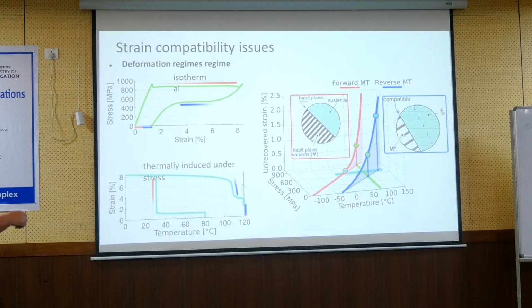So what? Maintaining the temperature below austenite start, right? What is the temperature? Okay, this is just the figure which shows the superelasticity at probably quite high temperature, so the stress is very high. We normally don't use 900 megapascal, it's too much. What are the temperatures in those tests? It's not stated. I estimate, if this is a superelastic wire, something like 100 Celsius, above Af. It's about 100, but it doesn't matter.